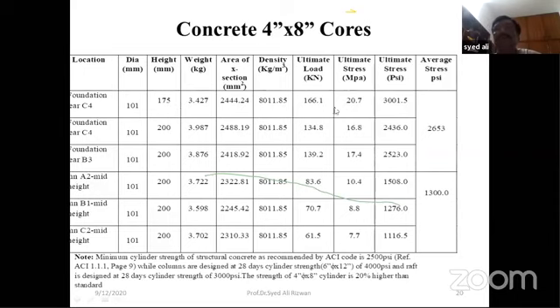So in the foundation, you can see the average stress of concrete, 2,653 PSI. If you divide this by a factor of 1.2, then the minimum structural concrete should have a strength of 2,500 PSI, according to the ACI code reference, at 28 days.